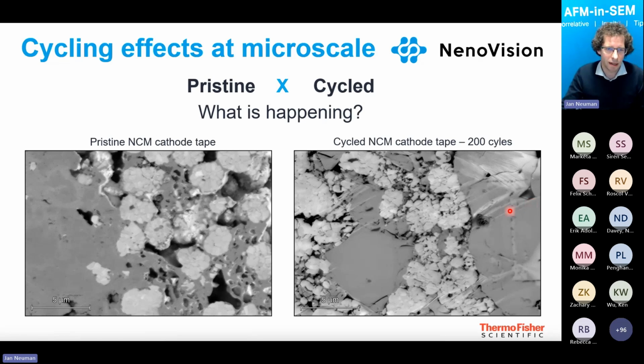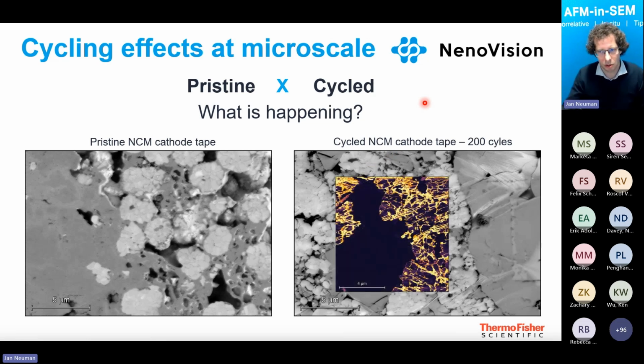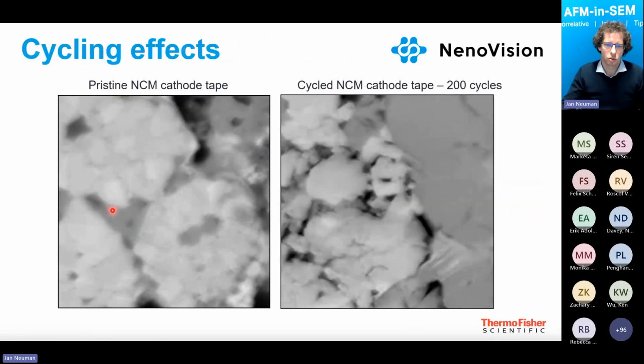What you see here are SEM images of the NCM cathode tape in the pristine stage and after cycling. There is not that big a difference. Maybe you can start to see the cracks, etc. But then we can start to think about the conductive measurements and conductivity changes. This is how the conductivity looks after the 200 cycles. Then if we dig into the details, we can select the area of interest in reasonable areas where we have some cathode materials and areas which we can compare. So we can zoom in and make SEM images.